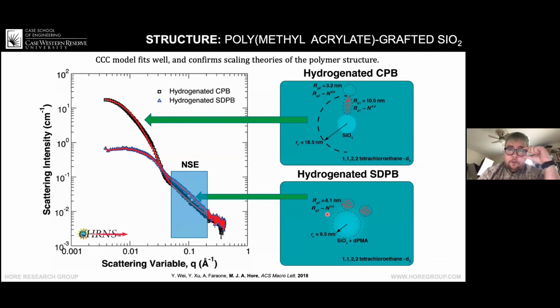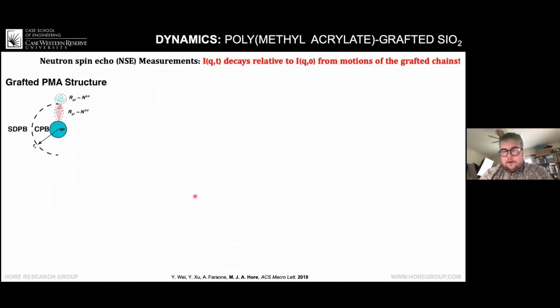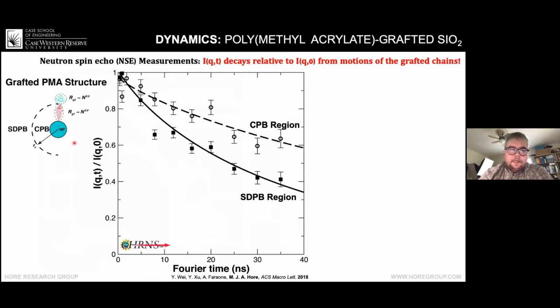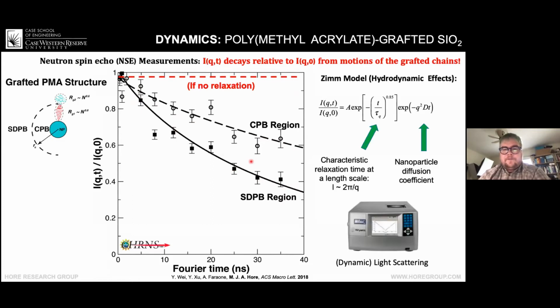So spin echo is able to probe the relaxation times of the polymer chains at different length scales and at different times. In terms of the length scales, or the Q space that it's sensitive to, we're looking out here at these regions of the scattering graphs. So again, this is what spin echo data looks like. This is the normalized intermediate scattering function. But if you know nothing about intermediate scattering functions, and if you know nothing about spin echo, what you can see by looking at this graph already is that these open points here, which describe the relaxation of the stretched region, are quite distinct from the filled points here, which describe the relaxation of the outer region. And what I'll tell you is that if we were not observing any relaxation, then this function would just be 1. So we can already see that there is a difference in the relaxation times of the inner and the outer regions of the brush. So we have to fit this somehow.